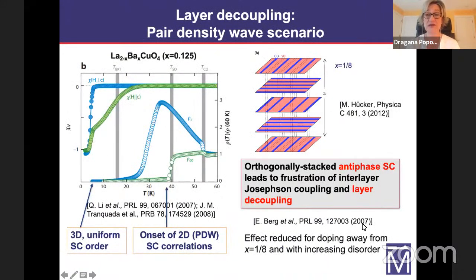by Berg and others to describe some surprising experiments on LBCO at 1/8 doping, a material which has a stripe order. So in particular, they found an unusual anisotropy: once charge and spin stripes are established, the in-plane resistivity shows a strong drop of an order of magnitude, but the out-of-plane resistivity continues to increase. The in-plane resistivity later goes to zero in a manner that is consistent with the Berezinskii-Kosterlitz-Thouless transition, in other words, with a superconducting transition in 2D, but the 3D uniform superconducting order is established at an even lower temperature.